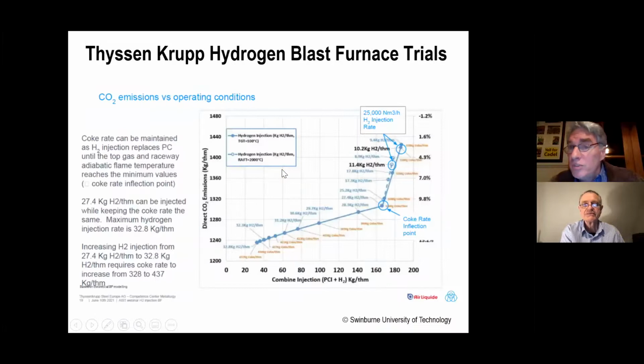And they've done some tests and some calculations. One of the lead engineers sent me this slide. It's very nice of him to share that with you. And he's showing his calculations here about how much hydrogen they can put in. And what they say is that the limit is 27.4, a very precise number from the Germans, I thought, 27.4. And that gets you down on this graph to about 1,200 kilograms of CO2 per tonne of production. So in other words, they're only cutting the production by a bit, and they find that once they try to put more hydrogen in, they actually start making things worse because they have to compensate for these endothermic reactions. And you'll see that the graph is going up as you push more hydrogen in.